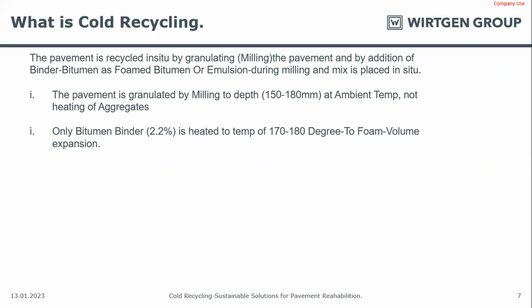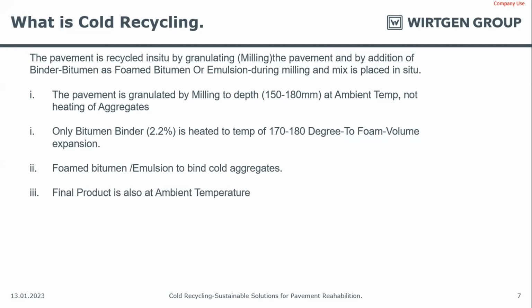Here foam bitumen or emulsion is used to bind the cold aggregates. In emulsion, as you know, water makes up to 30%, so 1.3 times the amount of emulsion is required to add the same amount of bitumen. If we go for emulsion, it just creates patches on the surface of the aggregates. Whereas in the case of foam bitumen, we add 2.2 to 2.4% of VG30 bitumen, so it covers the entire surface area of the aggregates. Hence we get more bond and better riding quality.